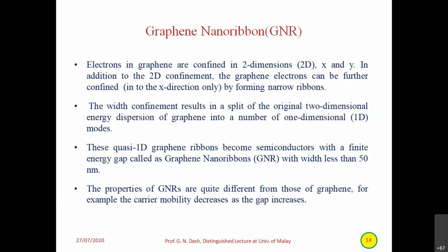Forming narrow ribbons. The width confinement results in a split of the original two-dimensional energy dispersion of graphene into a number of one-dimensional modes. So if we just cut the graphene into small nanoribbons, less than 50 nanometer, what happens? The original bands which were there, they develop several mini bands inside the main band. So there is a band gap between the mini bands, and that creates the band gap.